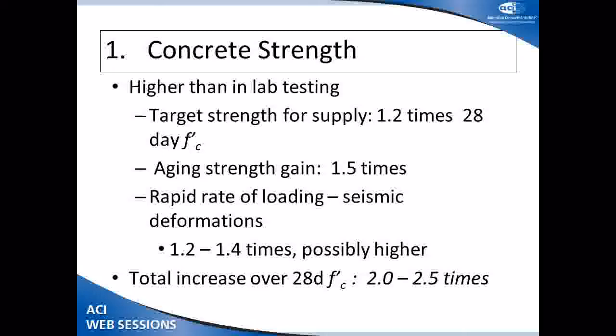Concrete strength. The concrete strength we are seeing in the structures is obviously higher than the lab concrete that we've used to develop our engineering equations and recommendations. For a start, a supplier of concrete will be targeting about 20% higher than the engineers specify. Age enhancement of strength is about 1.5 times the 28-day strength.